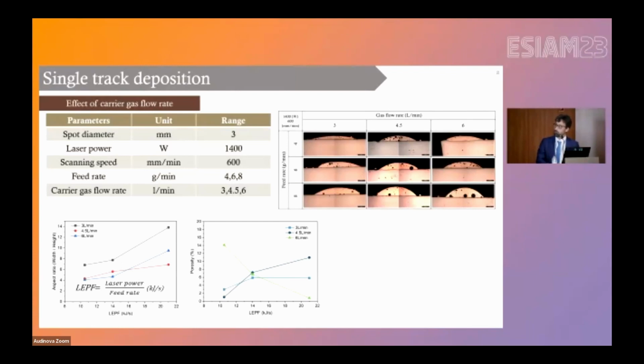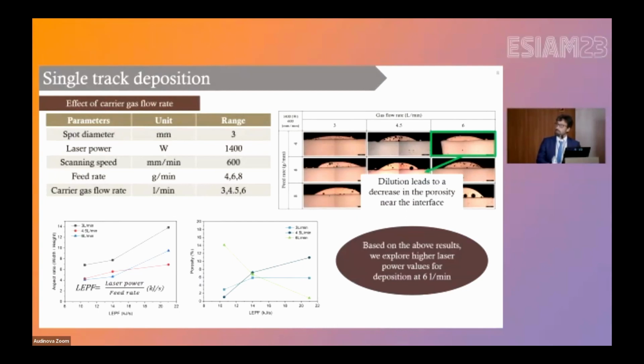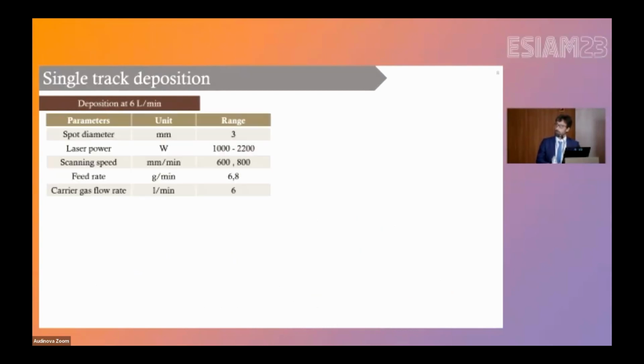And so we were able to find combinations of process parameters able to achieve a good aspect ratio, a low porosity, and the presence of dilution. Also interestingly, in some combinations, as you can see here, in which we have dilution, so the interface is no longer sharp, dilution is generally accompanied by a low porosity. So we were basically interested in such process parameter combinations able to achieve this double goal.